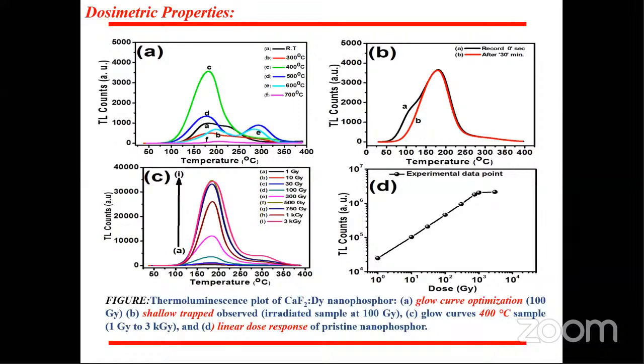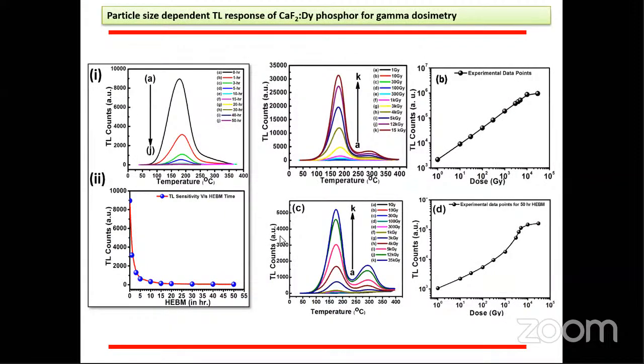Then what happens? We used the ball milling technique to reduce the particle size. This pristine sample has a particle size of around 150 to 100 nanometer, and later on we used samples of different particle sizes. This figure indicates the 0-hour to 50-hour samples and how the sensitivity decreases. This is the 10-hour sample and this is the 50-hour sample. The 10-hour milled sample shows a dose range response from 1 gray up to 12 kilogray, and here it does not show any linearity.